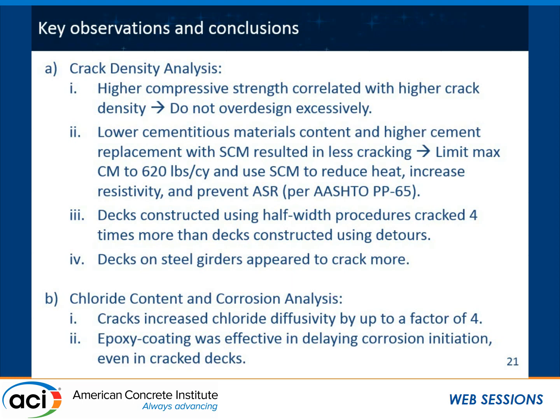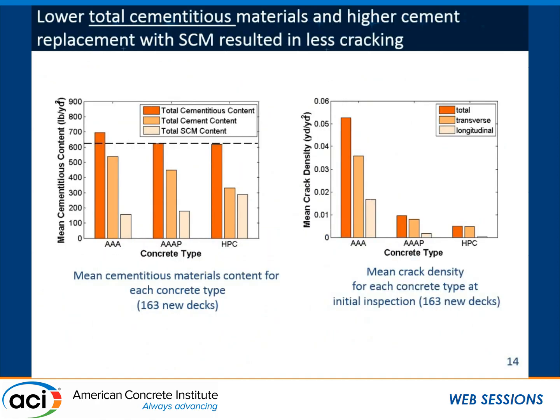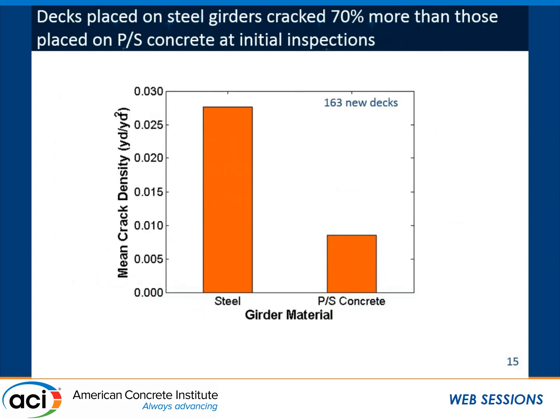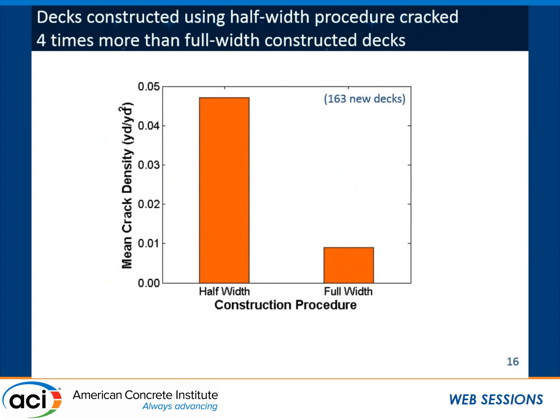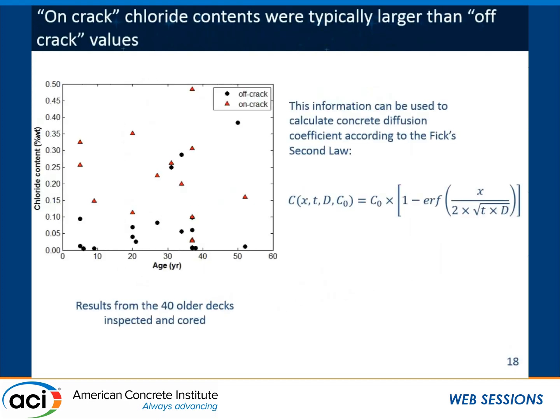Well, there were two sets of bar graphs that I showed you. These are all based on initial construction, so all of this data was collected within a span of 2 weeks after placement of concrete. For the older decks, you're absolutely right, there is variability in age. I did not present the crack density as a function of age. We actually didn't find a strong correlation between crack density and age. We had some very old decks that had few cracks, and some young ones that had a lot of cracks.